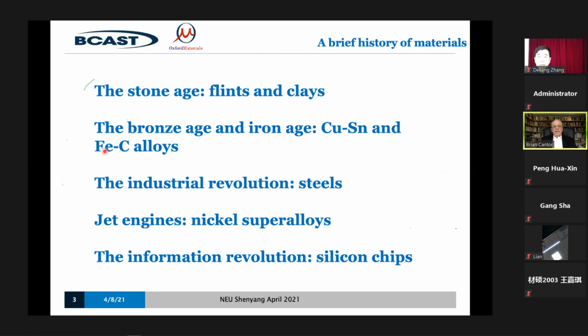Now people began to make bigger and better fires. Basically, they learned how to make chimneys. And if you put a chimney on a fire, the fire gets hotter, and you then find that you can make iron by smelting as well. The carbon in the wood, again, will reduce the iron oxides into iron, but iron is different to copper or tin or lead. It dissolves quite a lot of carbon, a few percent, not a massive amount, but it dissolves a few percent of carbon, and that produces what we call irons.